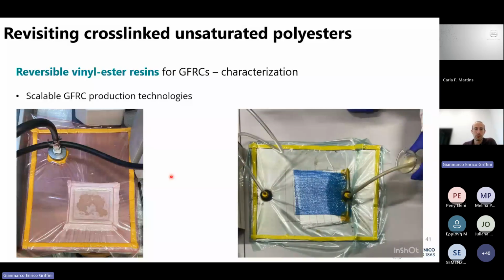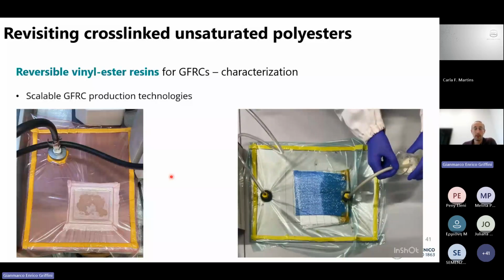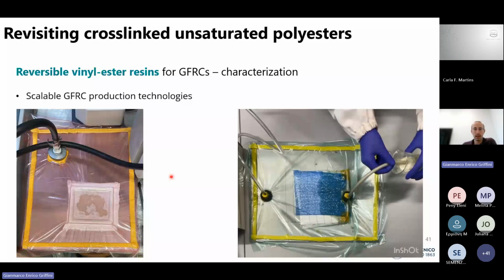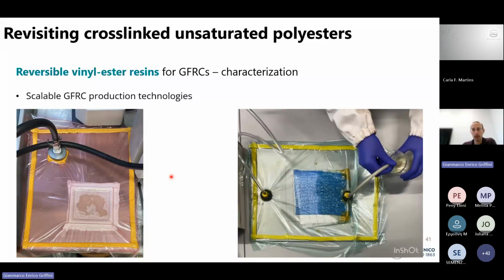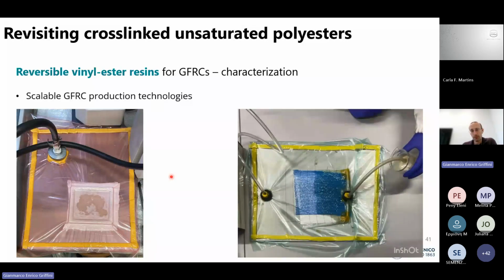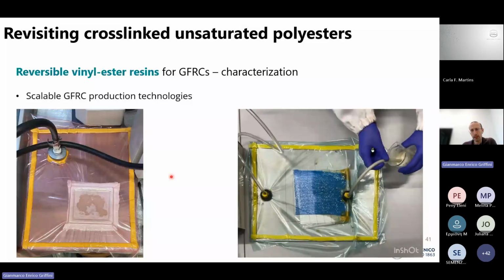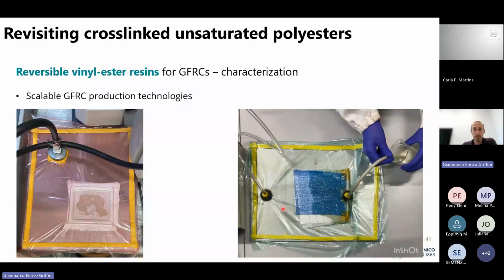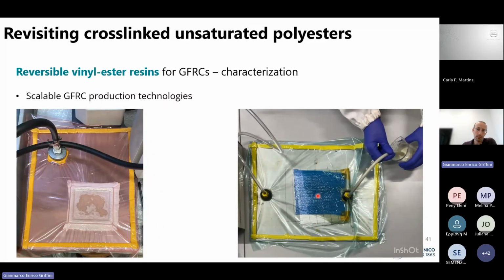In our case, we focused on the infusion, which is typically the technology for obtaining fiber-reinforced composites. And by, again, modulating the viscosity through formulation, we could obtain a very good flowability of our resin, as you can see from the video reported here. This is some of our people working in the lab on composites, and you see that the actual fiber mat can be very well wetted by the introduction of the resin through vacuum-assisted infusion.